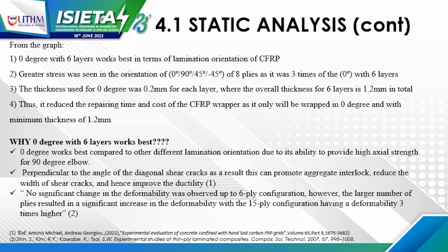So why does 0 degree with 6 layers work best? The 0 degree can provide higher axial strength, and because it is a 90 degree elbow, the 0 degree wrapping method provides a direction perpendicular to the angle of the diagonal shear crack, and it can also promote aggregate interlock, reduce the width of the shear crack, and improve the ductility. As we can see, there's a 0 degree with 8 plies, but it shows slightly higher stress than 0 degree with 6 plies. A research study found that no significant change in deformability was observed up to the 6 ply configuration. A larger number of plies doesn't mean an increase in strength, but it increases the deformability. This is mainly due to the load and stress being applied to the defected area.